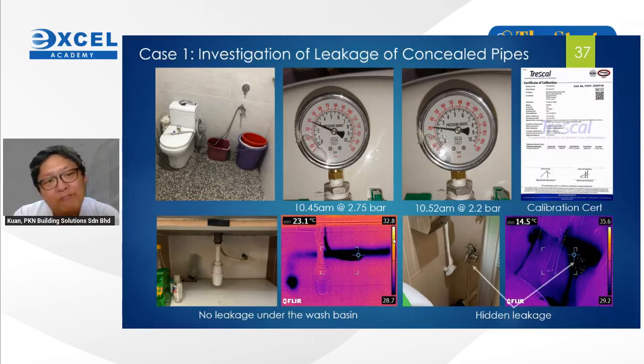Concealed pipe, as it implies by itself, is hidden. We don't know, it's all hidden. But to check if there is any leaking, we can do a pressure gauge test, and the pressure gauge test showed that at 10:45 a.m. the pressure was 2.75 bar, and in 7 minutes it dropped by 0.5 bar. So we can be sure that some leakage happened inside the wall, in the domestic pipe, and the pressure gauge has been calibrated.